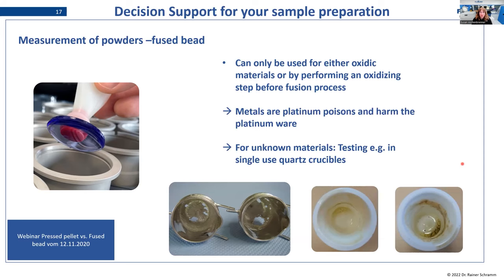Another thing that is a little disadvantage about using fused beads is that the fusion can only take place for oxidic materials, or you have to perform an oxidizing step before the fusion process. Why is that? Metals and reduced materials, they are platinum poisons. They just harm the platinum ware. So then you have very, very bad pictures, as you can see, like this one below. So these crucibles, they are just going to have to be replaced. And this is because of a metal sample that destroyed these crucibles.